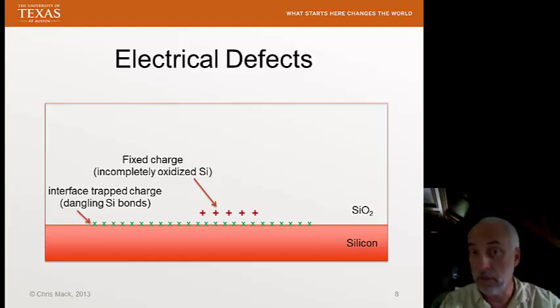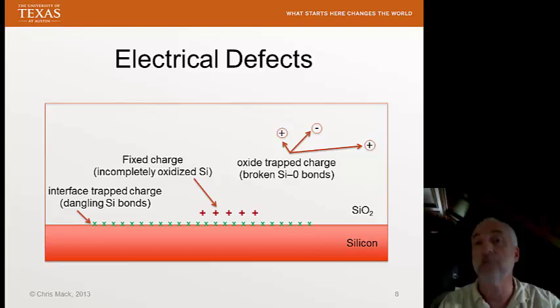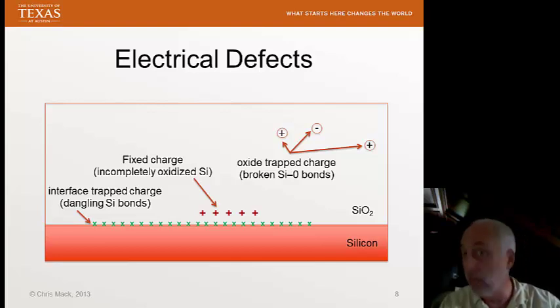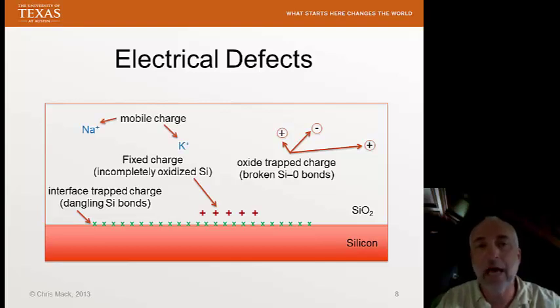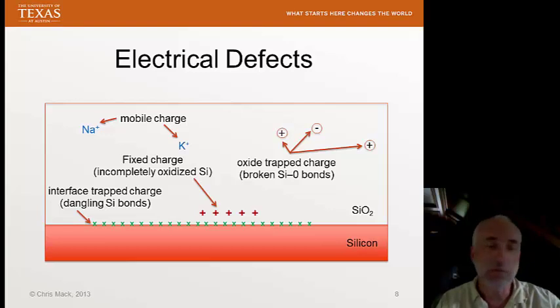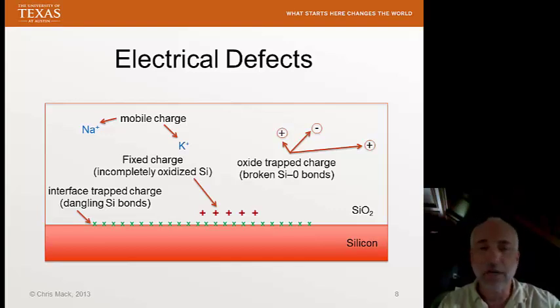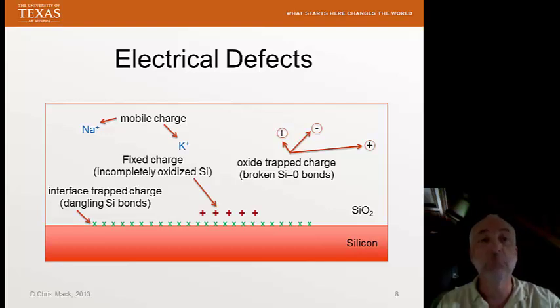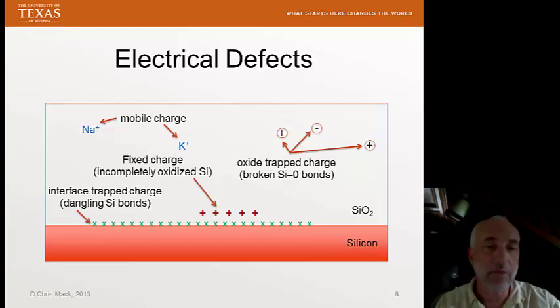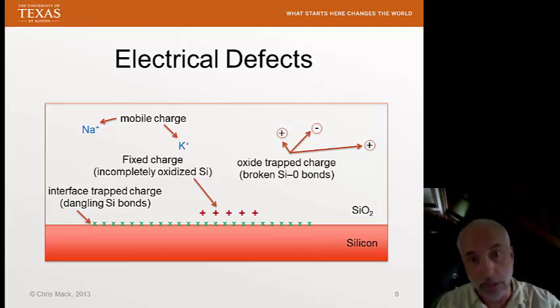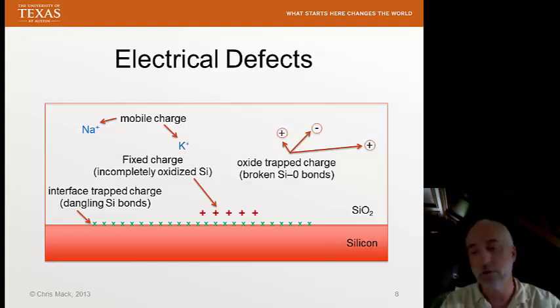In the bulk, we can have electrical defects too — trapped charge in the oxide itself. These are broken silicon-oxygen bonds that, as a result of being broken, can trap either a positive or negative charge. Finally, we can have contamination. Things like sodium and potassium are the most damaging contaminants in our process. Some of the very early work in semiconductor technology in the 60s found it very difficult to make MOS technology function until we learned how to get rid of these contaminants, because they're mobile — they can move around under the influence of an electric field. We want this to be an insulator; if we apply a voltage and charge moves, that's a current, which is not a very good insulator.